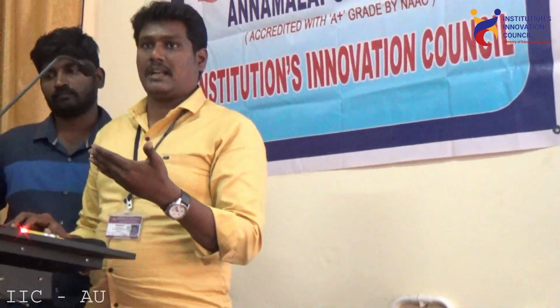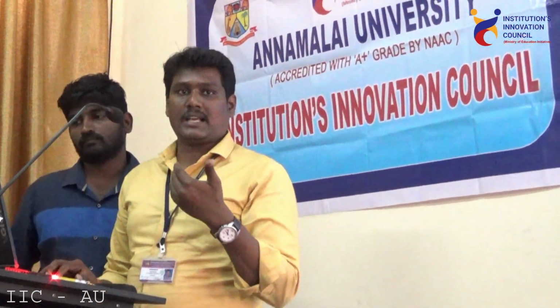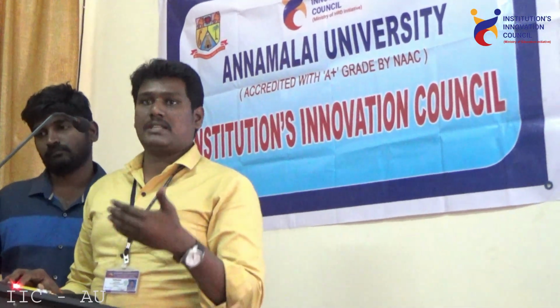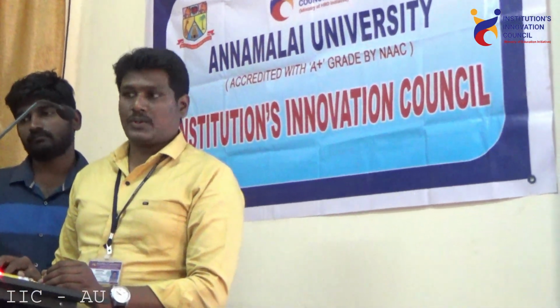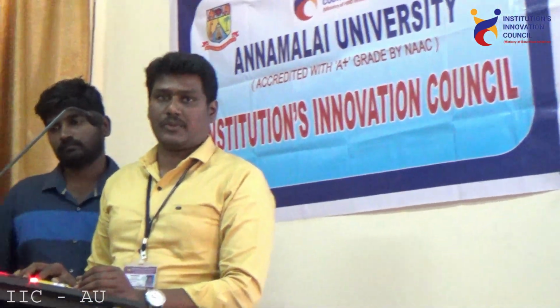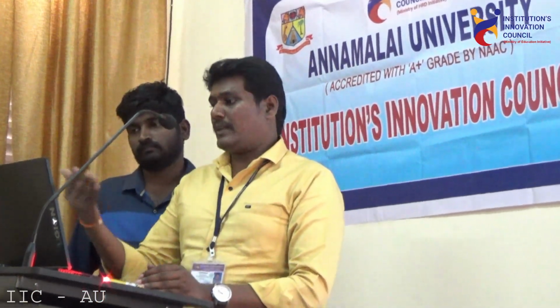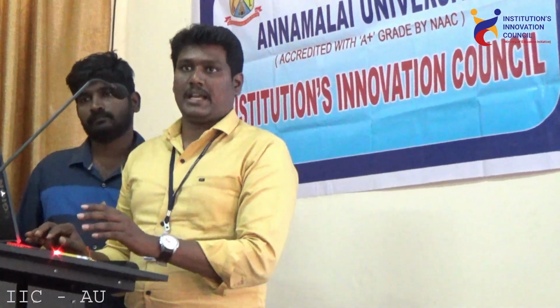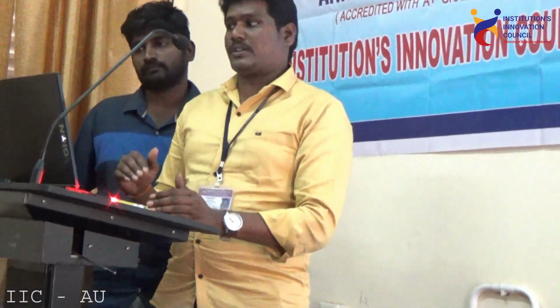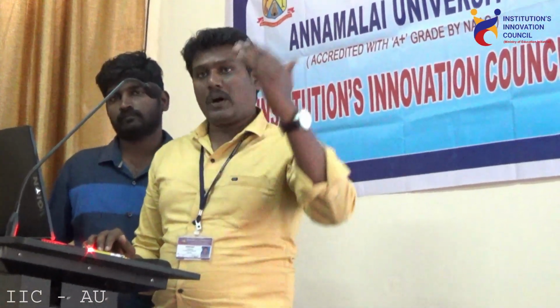This image is taken by microstructural analysis. First the sample is taken out from the produced component and it is polished and etched, and we have found pores. Then it is given to the image analysis software, named ImageJ, where we have pointed out the locations of the holes. Then using some threshold, we get a better look at the porosity alone. Through that we have calculated the number of pores in the sample, the total area of the pores, and the pore diameter.